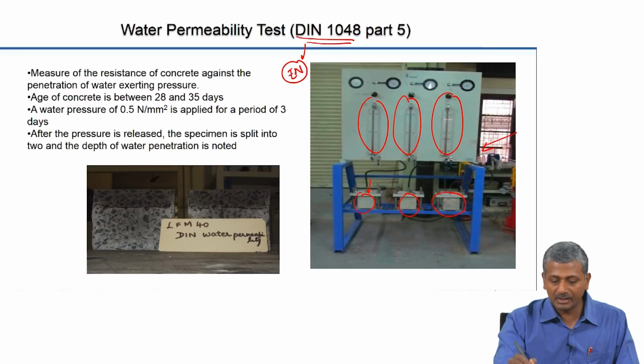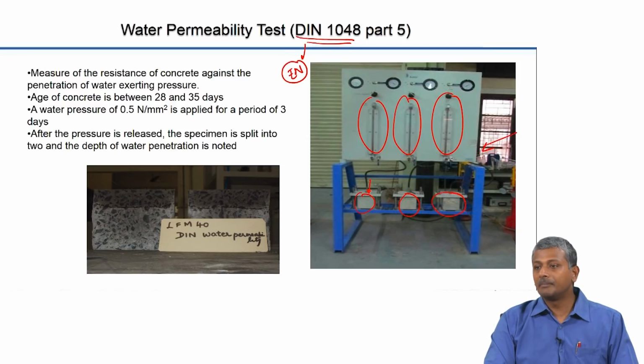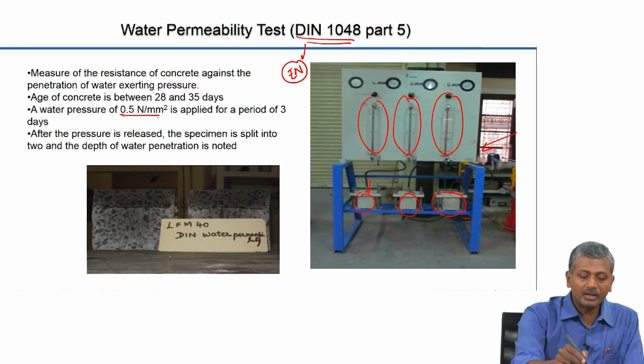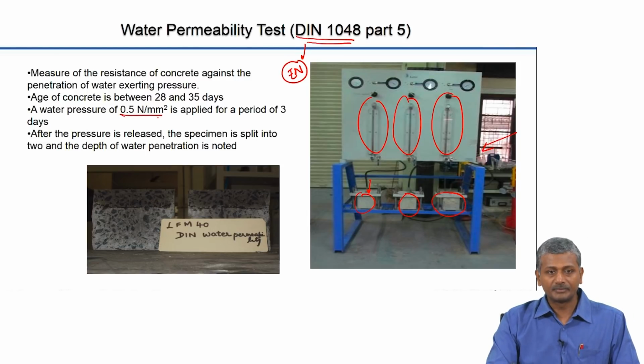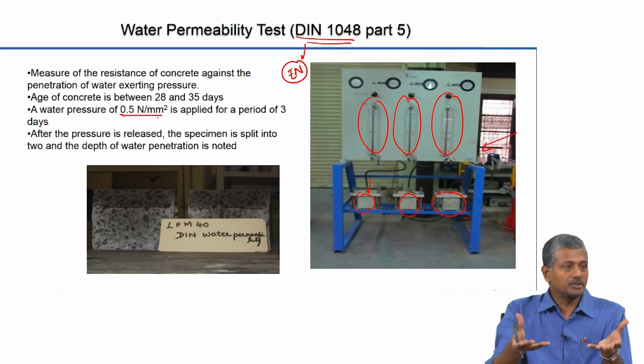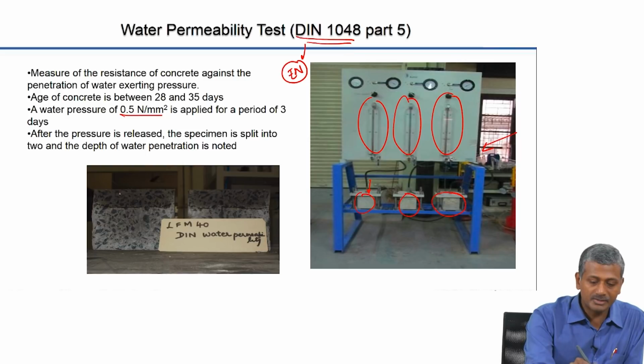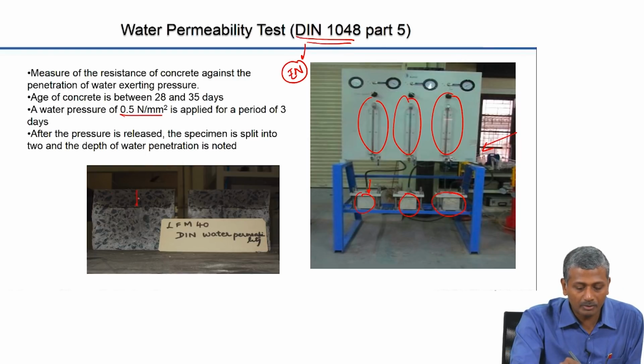So this water basically comes through that tube there, penetrates the concrete, and after 3 days of application of 0.5 megapascal pressure or 5 bar pressure, you split the concrete open and measure the depth of penetration. So this is showing you the depth of penetration of the water into the concrete.